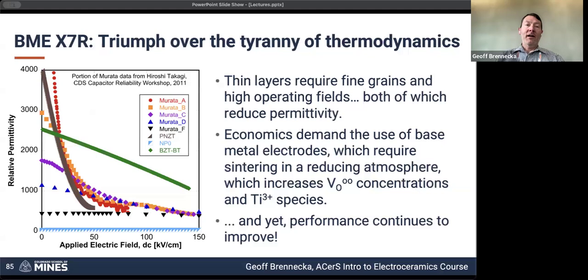In addition to that, as we apply an electric field, so this is applied electric field, the relative permittivity drops. So this is commercial barium titanate capacitors. As you apply a field, the relative permittivity drops. One way to think about that is if you've got these springs that we talked about before, if we pre-stretch that spring by applying a DC field, the amount of additional permittivity that we get by having an AC wiggle on top of it is smaller and smaller.